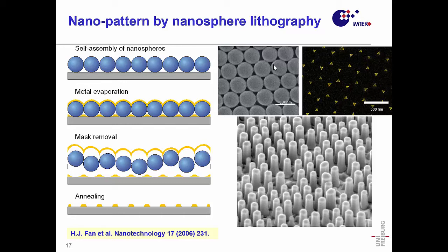I would not suggest using that immediately for growing the nanowires, because you would end up with a lot of small wires coming out. First do an annealing step, and then you have a kind of de-wetting of the surface, and then you can grow, and you are getting nanowires or pillars depending on the size. With the size of the spheres you are controlling the size of these dots a little bit.